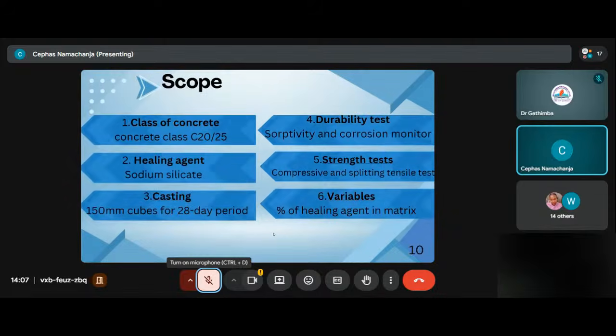For our scope, we'll evaluate and base our study on concrete class 20 or 25 that we'll prepare using standard PPC cement, standard aggregates, and sand. Our self-healing function will be carried out through integrating silica gel granules filled with sodium silicate with the concrete matrix. We will cast concrete molds of 150 millimeter by 150 millimeter cubes. We'll cast an average of about 15 molds. 3 molds will act as our control experiment. 12 molds will vary the amount of healing agent by 0.5%, 1%, 1.5%, and 2%.